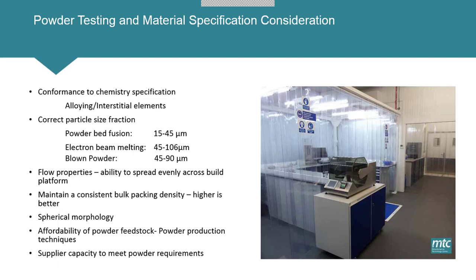So we know what we want to measure, but what are the right properties, or what do we think are the right properties for an AM powder? Firstly, you're never going to choose your AM powder based on how it flows or how it packs. The first thing is the chemistry, right? So any AM powder we order, first thing you want to check is you've got to get the right chemistry. Correct particle size fraction is probably the next most important. So depending on what AM method I'm using, I have very distinct size fractions. For instance, laser powder bed fusion traditionally would use 15 to 45 microns. Electron beam melting, because of the way it works, has something slightly larger.